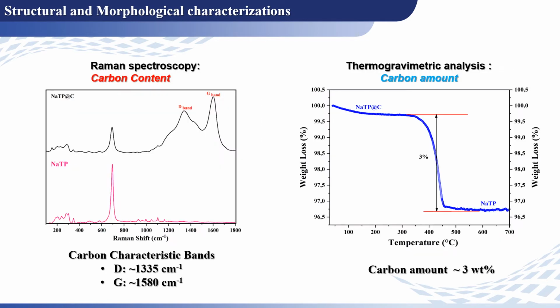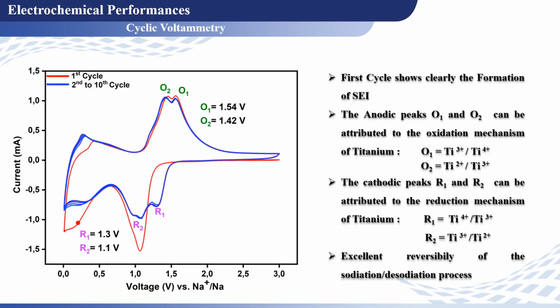Raman spectroscopy was performed to investigate the carbon content in this coated sodium titanium phosphate. As the results show, 2 additional broad and overlapping bands are observed, the D and G bands, characteristic of carbon. And also, thermogravimetric analyses were investigated to estimate the carbon amount in the composite material. As we can see in the results, the amount of amorphous carbon is about 3%.